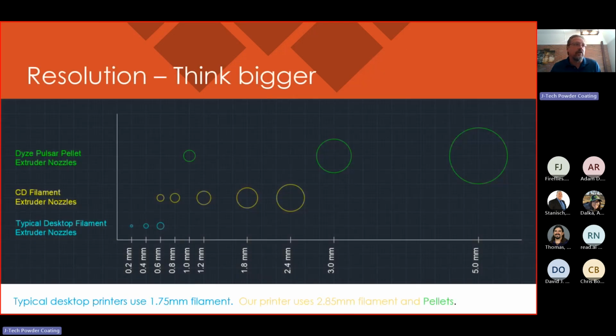So on resolution, you've got to think bigger when you're doing LFAM. For printing large models, the number one thing you can do to reduce the print time and cost is increasing the layer height and the nozzle size. A desktop printer is going to have nozzles of 0.2 to 0.6 millimeter diameter. 0.4 is most typical. Layer heights are going to range from 0.1 to 0.3 millimeters. That's great for creating small detail parts, but results in large parts taking excessive amounts of time, think hundreds of hours.